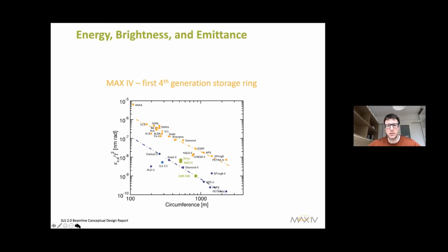In this graph, you can see in orange all the third generation rings. This is the current, or past, established technology for synchrotron storage rings, and they lie around this very nice line that connects the circumference of the ring and the emittance. All the blue or green dots represent the fourth generation storage rings, out of which only the green ones are operational rings. And MAX4, as I said, was the first one to establish the technology. You can see the big difference between these two groups, the third and fourth generation. So a lot of new science can and will be done using the technology that MAX4 brought.